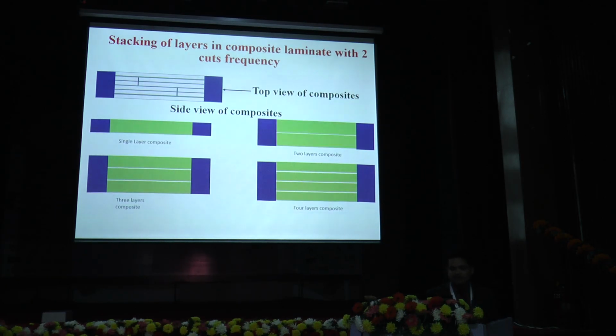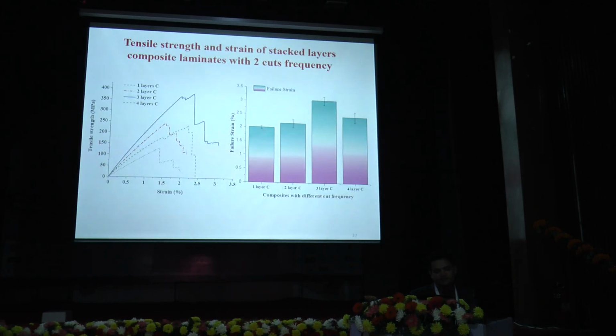In the 3rd case, we have done stacking of layers and introduced only 2 cuts, but increased the stacking sequence, meaning layer 1, layer 2, layer 3 all have the same number of cuts. We have seen that as we increase the number of layers, this behavior changes.